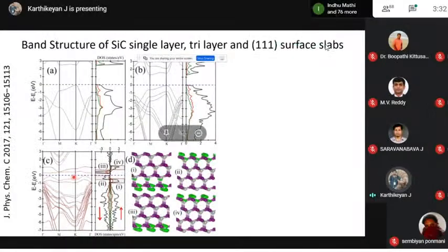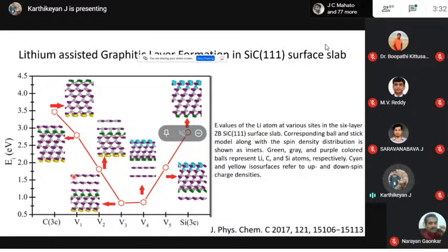So if you add capping atoms on the surface, you are going to eliminate these surface states, and you are going to open up a very large band gap for your silicon carbide. So then we studied the lithium adsorption on this silicon carbide. As usual, we want to understand the energetics of lithium on this silicon carbide.